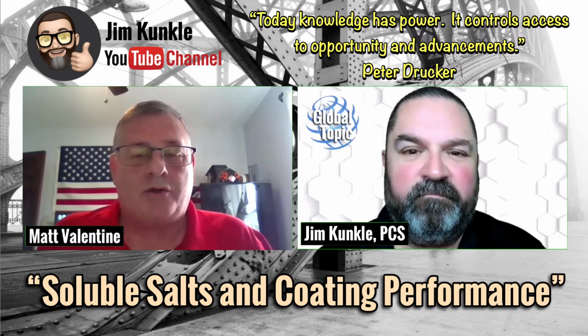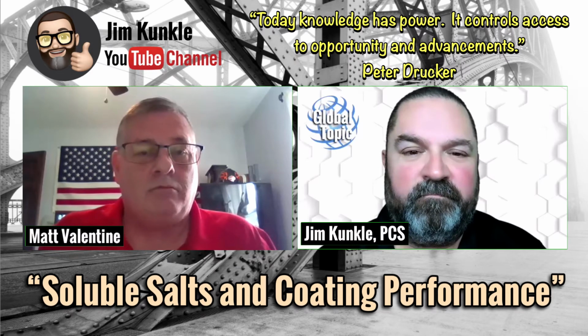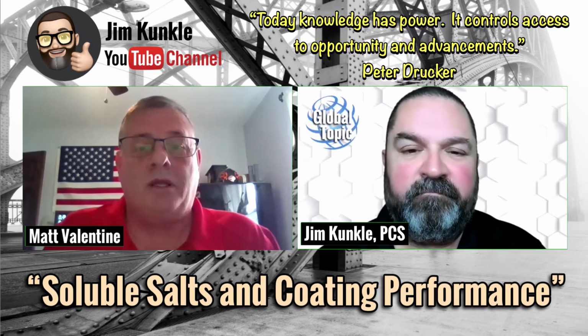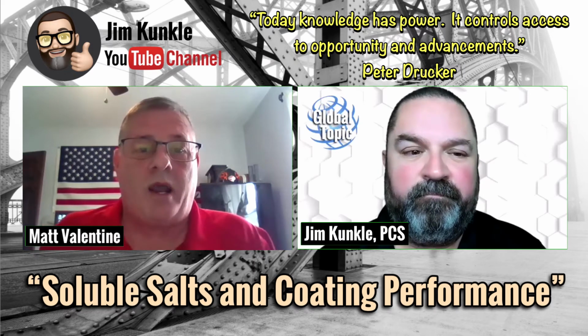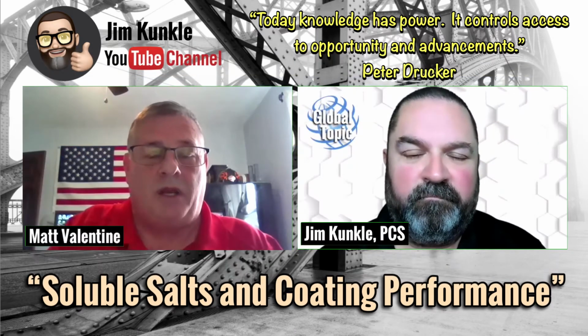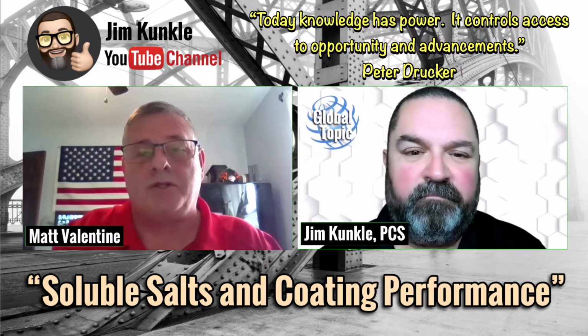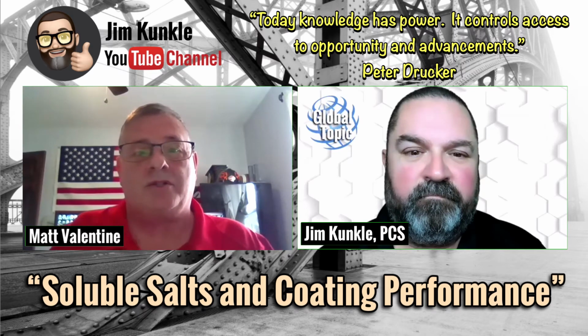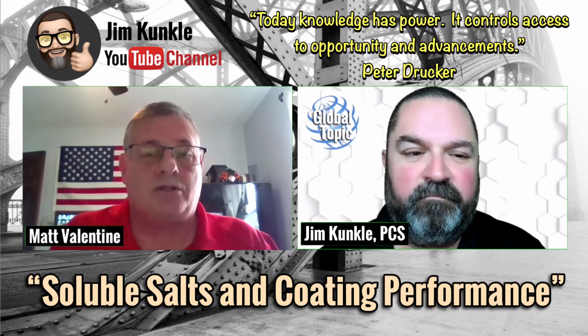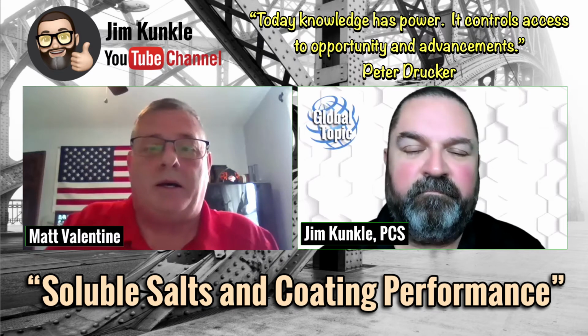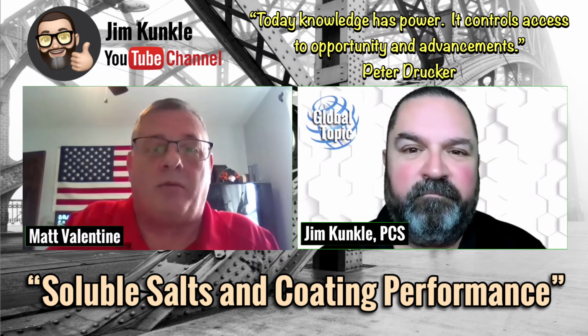Salt will attract moisture and absorb it into the salt. So that's why, when you have the salt ion underneath the coating system and then the moisture passes through the coating, that creates the corrosion cell. And our goal is to eliminate the salt ion completely. So when that moisture passes through the coating, there's nothing there to react with it. So you don't have that problem.